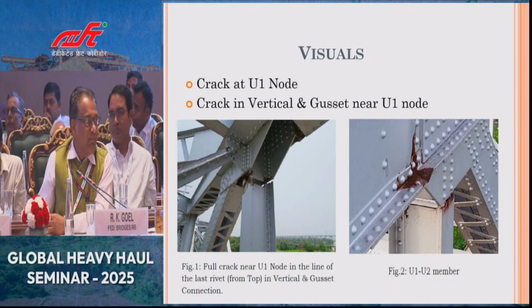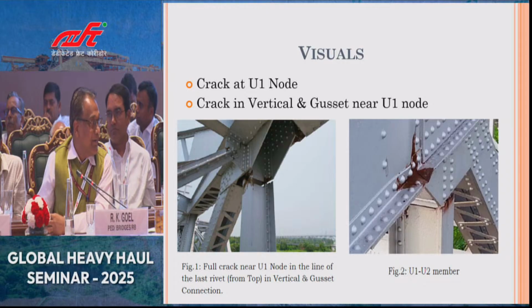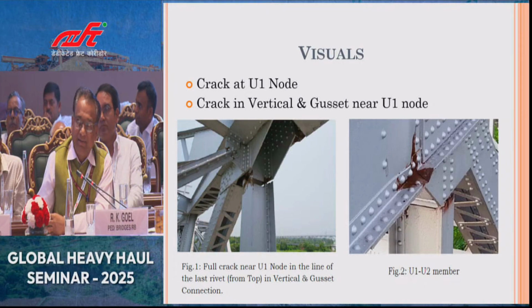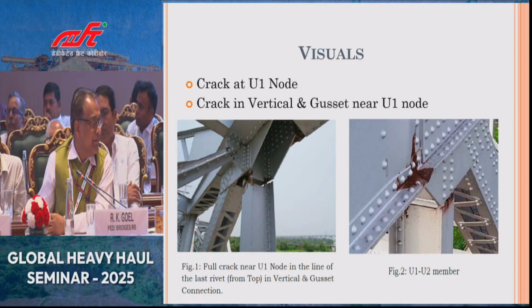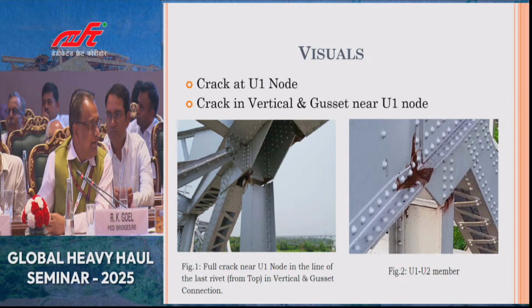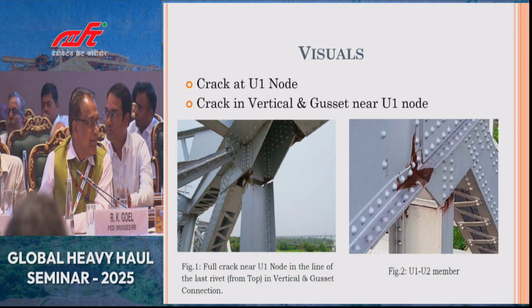And this top boom, which is always in compression, had an L upon R ratio which doubled after this fracture. So when the L upon R ratio doubled, this member was bound to buckle. So it buckled actually. And you can see because of the high compressive stresses, these members distorted. With this distortion, the complete girder basically became dysfunctional. And it is a very important route, having a GMT of about 80. We had to sustain the traffic. So it was a big challenge to control this girder and somehow make the traffic operational on this.